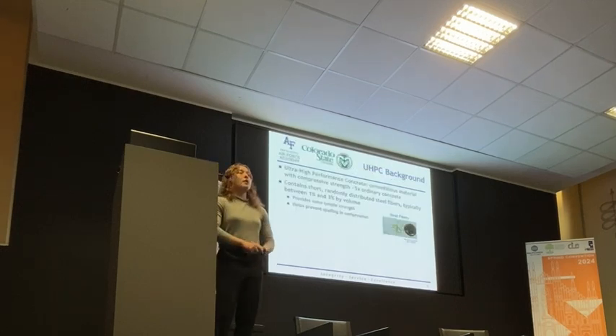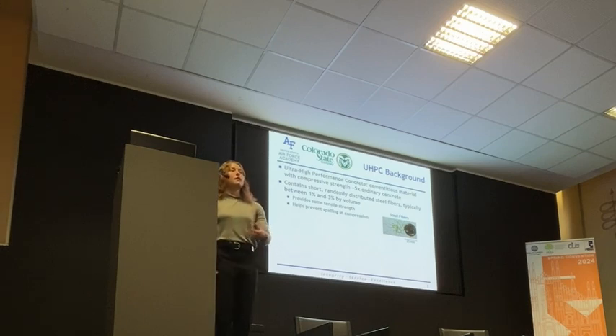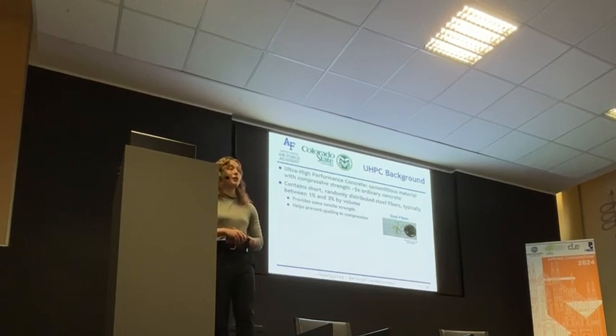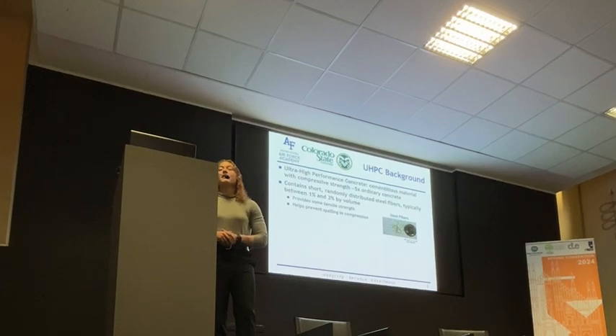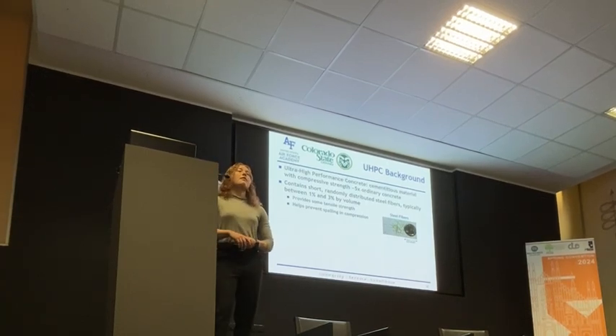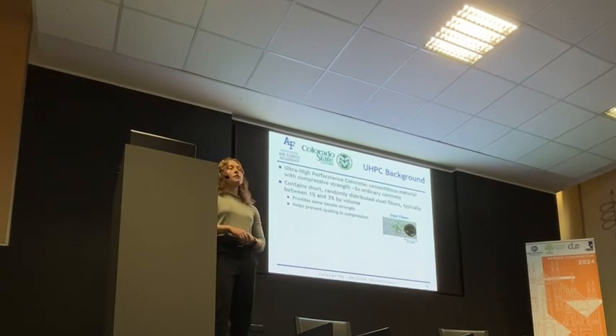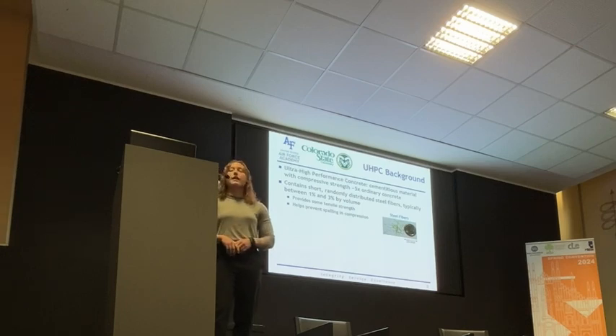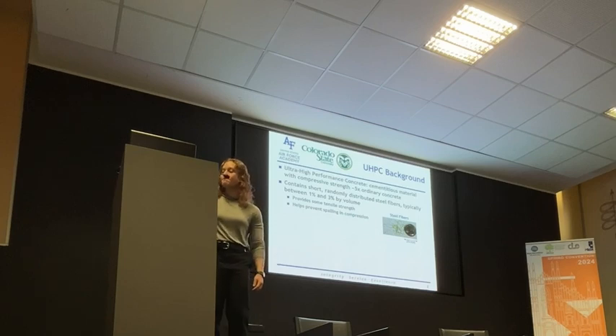So some background on what UHPC is. It seems like a lot of you are familiar with the material, but in short, ultra-high performance concrete is a cementitious material with a compressive strength relatively 5 times greater than traditional concrete. Very impressive material. It contains short, randomly distributed steel fibers that is usually 1 to 3% of the volume of the specimen. It provides some tensile strength and it helps prevent spalling in compression.